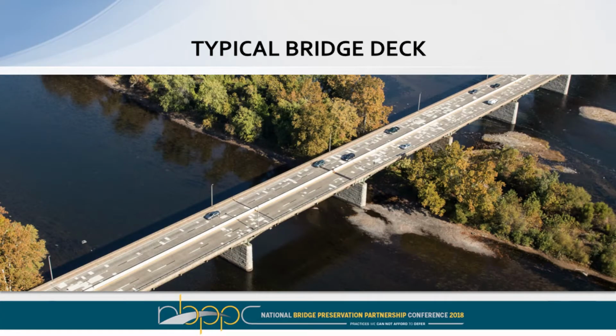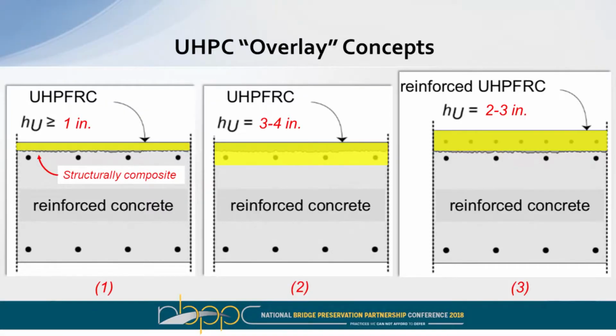But the idea here is really to get onto the bridge deck before it's gotten to the point where it needs to be fully replaced. So can we do a partial depth removal and rebuild that back with UHPC rather than having to replace the deck in its entirety? And so there's three concepts that have emerged over the years. Ideally it's really number one. We get on the deck early enough when the contamination hasn't gotten too far gone, and we only have to remove a marginal amount of cover, maybe an inch, maybe an inch and a half, and then we can build that back with this very durable, impermeable material.